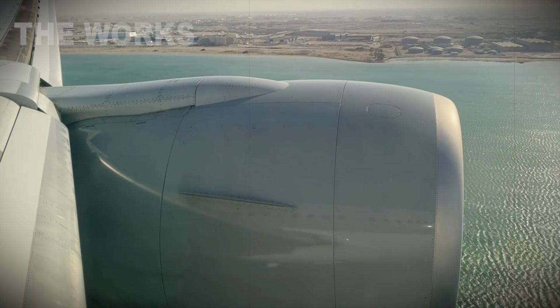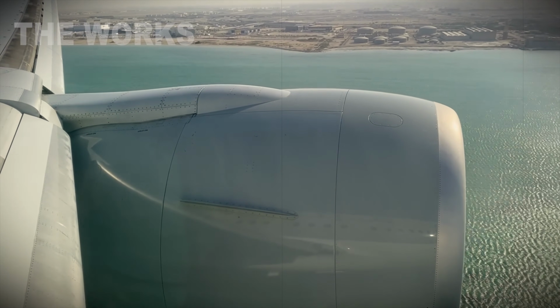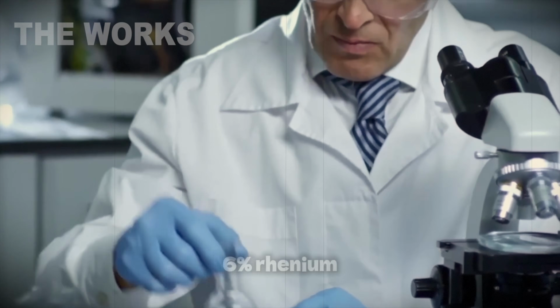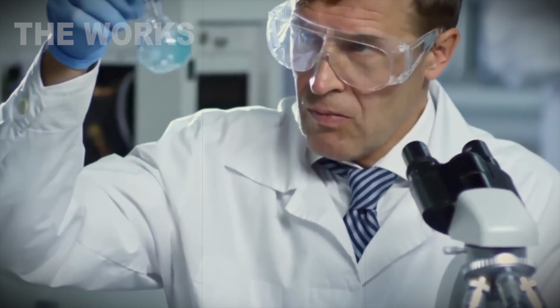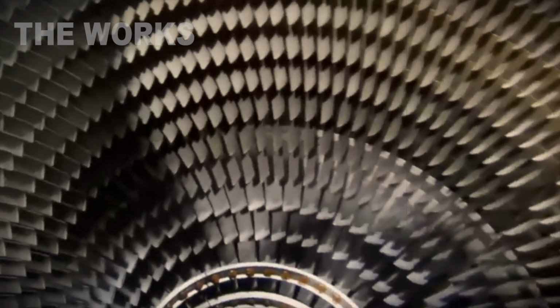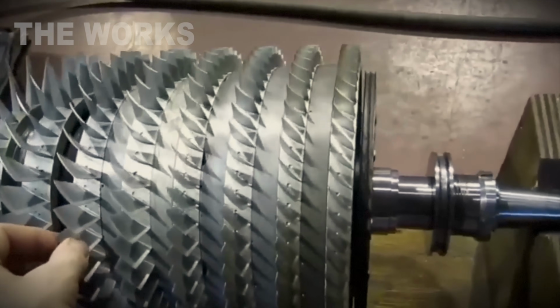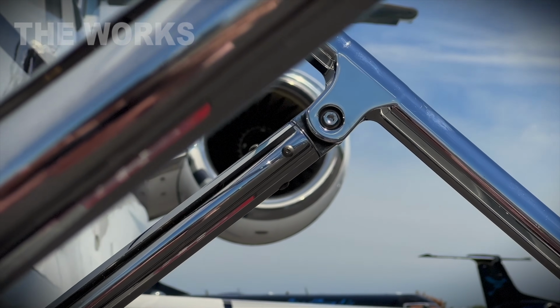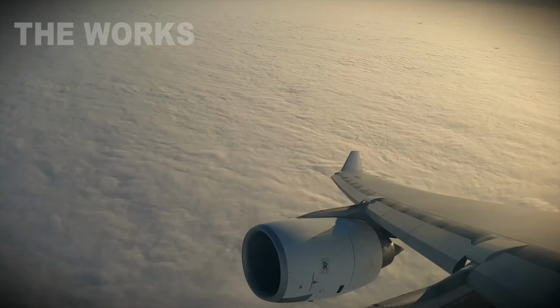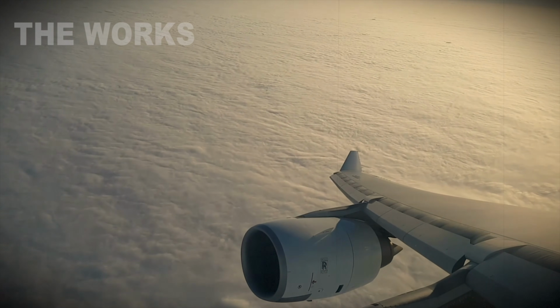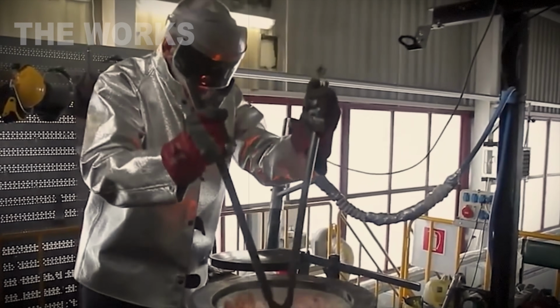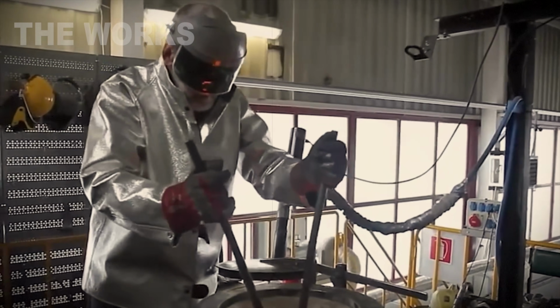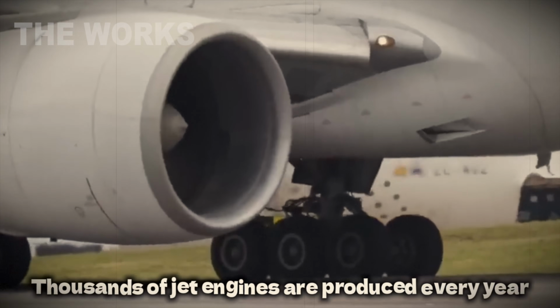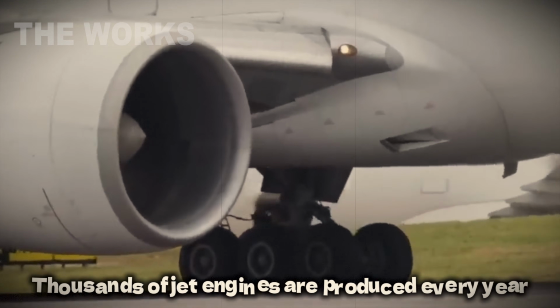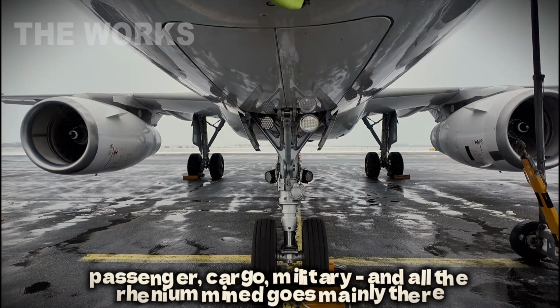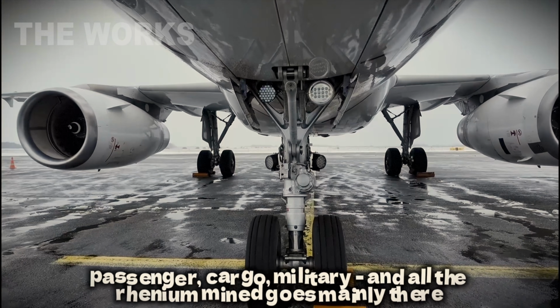Modern superalloys contain up to 6% rhenium. A single turbine blade can hold anywhere from 5 to 20 grams of rhenium. One engine on a large passenger jet, about 13 pounds of rhenium in the blades alone. 13 pounds of metal worth up to $50,000 in a single engine. And a plane has 2 engines. Every year, thousands of jet engines are manufactured. Passenger, cargo, military, and virtually all the rhenium mined goes straight into them.